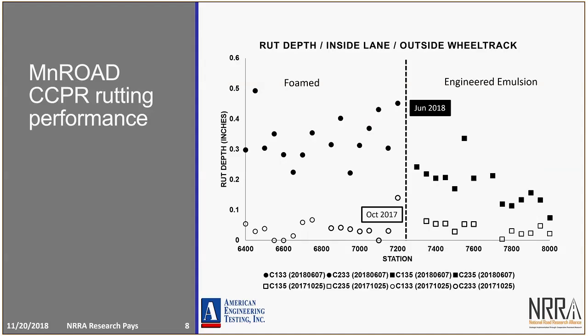And one thing that we've gotten from these cells is some rutting data that Dave Van Deusen recently provided. You can see that in October 2017, these are the empty symbols at the bottom, where we don't have a lot of rutting. Then there's the progression of rutting, and we've seen more rutting in general in the foam sections, and that agrees with the testing that we've done in the lab so far on the field mixes. We just completed the Hamburg. We don't have formal results ready, but the test has been run, and apparently the foamed mix was failing around 3,000 to 5,000 passes, whereas the engineered emulsion was holding up for anywhere between 7,000 and 9,000. So that general rule of thumb agrees with what we see in this data.